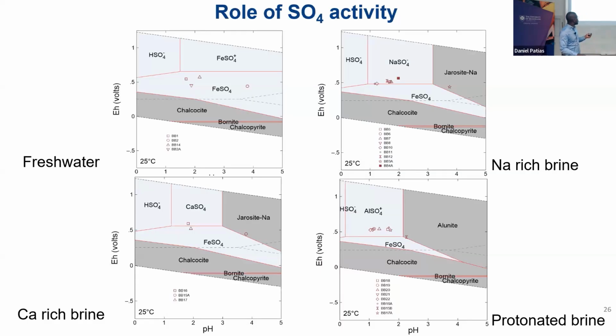More so, if you form more jarosites, that's also not good because then your ferric is going into forming jarosite rather than getting your copper out for you. So we think that you could form things like aluminum sulfates, which is not consuming your ferric and is helping your ferric stay in solution to get your copper.